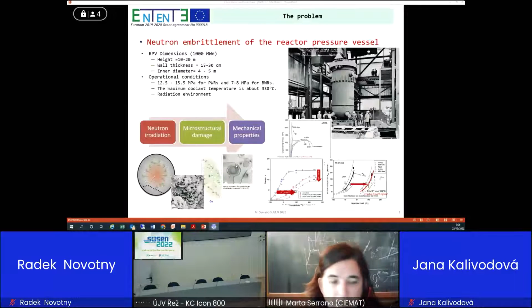So the problem that we deal with in ENTENTE project is the neutron embrittlement of the reactor pressure vessel. It's not a new problem. It is very well known that the reactor pressure vessel material becomes brittle during operation due to the neutron irradiation. But we need to take into account that this component, the reactor pressure vessel, is not replaceable. You cannot replace the vessel, at least economically. And it is a large component. And the operating condition is around 10 megapascal and around 300 degrees Celsius. And the radiation embrittlement is the key point.